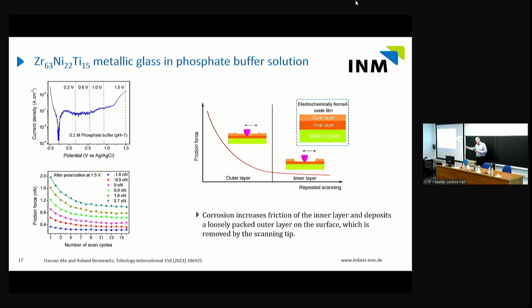So after we polarize this, after we go to an oxidizing potential, we go back to open circuit potential, and then we do friction force microscopy on the surface. And the result is in the lower left. The problem is, originally we wanted to look into the active process, but that's very difficult. If you change the potential while you're scanning, you get a mess of results. And the reason is that oxidation produces a soft layer on top of the metallic glass, which the tip is removing all the time. So we have two time dependencies. One would be the oxidation, and the other would be the removing of the oxide layer.